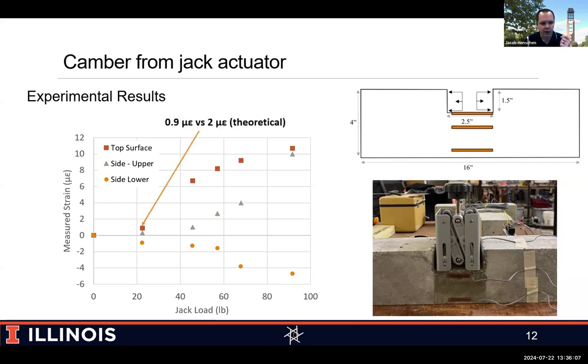However, as we think about that calculation of, if we apply 22 pounds, we should see about 2 microstrain. Well, we saw about 0.9 microstrain. When you start to consider that these strain gauges really are limited to about a microstrain for accuracy, the agreement is not too bad in this particular case. So that showed us that we're picking up and seeing what we expect at these lower loads in a controlled setting with this lab jack.